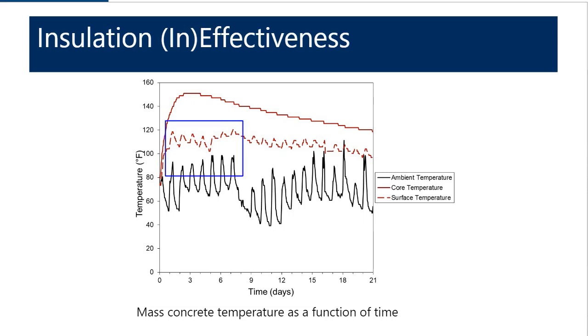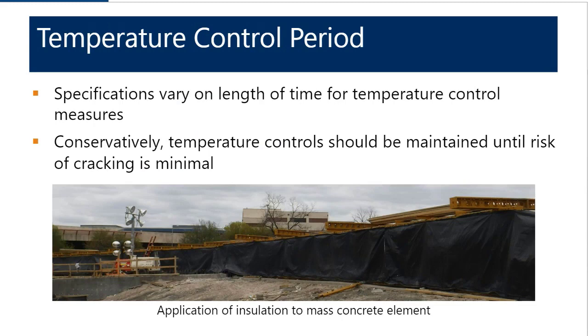And so you can see here in this area at the beginning of the temperature control period, the surface temperature is aligned with the ambient temperature. So how long does the temperature control period last? Well, it depends. As Elizabeth said, that's a favorite answer of ours. Sometimes the specifications state the temperature control period, but in general, the temperature control should be maintained until the risk of cracking is minimal.